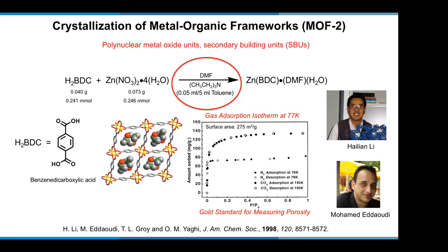So this was the very first proof of permanent porosity in MOFs, and it was very exciting. Except that the surface area was not so high. And so when you compare these to zeolites, they were sort of as good as some of the zeolites, but not as good as the best zeolites. To me, this was exciting because it showed that in fact, all that literature that preceded this work with the metal nitriles and so on, now there is a pathway to making MOFs that are architecturally robust. And now we have available to us the ability to exploit the porous structure.